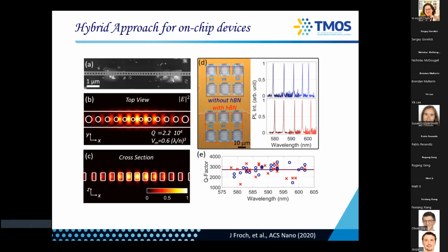So for the visible range in 2D hybrid materials, not too bad. You can, of course, go to silicon photonic crystals in the IR, get much higher Qs, but for our case, not too bad. Also, remember that the mode volume here is very small. It's a 1D PCC. Now, the trick that you can play is you can actually make the thickness of the silicon nitride cavity a little bit thinner, maybe by 5 to 10 nanometers, and then the HBN layer will actually cover the cavity and will complete your cavity.